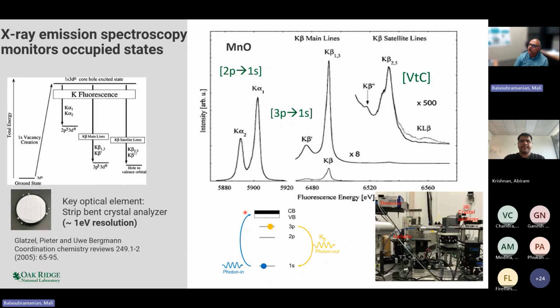So when this photon excites this electron, a core hole, that is an absence of an electron, is created in the 1s level. The system becomes extremely unstable because of the absence of this electron. And in the order of about a femtosecond or a few femtoseconds, the system relaxes back. The relaxation can take place by many methods, and chief among them are these so-called fluorescence emissions.